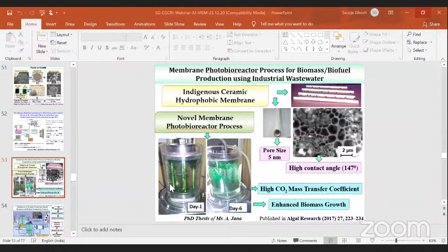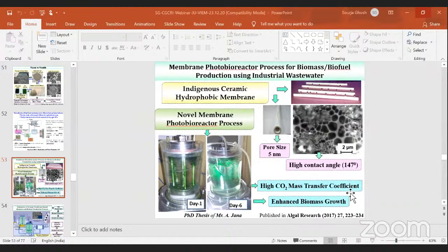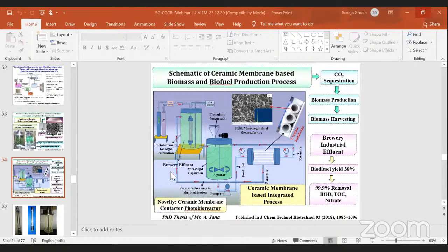So the Arthrospira species was cultivated using wastewater, and through this membrane module, CO2 gas was dispatched from time to time. And this shows the day 1 picture, and this is the day 6 picture of microalgal growth. So the membranes resulted in a high CO2 mass transfer coefficient, and enhanced biomass growth was observed. This is the schematic of the total process. This is the membrane photobioreactor, wherein the simulated flue gas is introduced in the wastewater medium, and biomass is grown here. This biomass is again harvested through a membrane-based filtration system. So this is the harvesting unit, wherein the ceramic UF membrane is used for concentrating or harvesting the algal biomass.